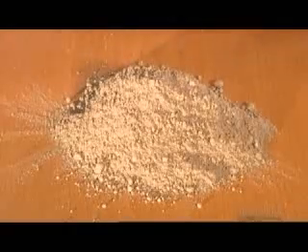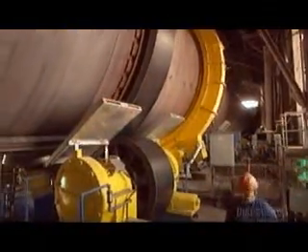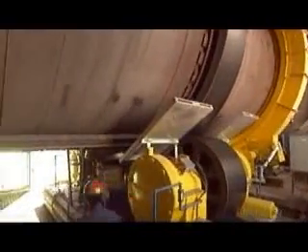This produces a dry rock powder called the raw meal, which then goes into a preheater. The temperature of the powder is 80 degrees Celsius upon entering, but within 40 seconds it gets more than 10 times hotter. This begins the process of bonding the minerals together so that they'll later harden when hydrated with water. The preheater is equipped with a flash calciner, which in about 5 seconds removes 95% of the carbon dioxide in the powder through a chemical reaction, isolating the lime — the most important element in cement.